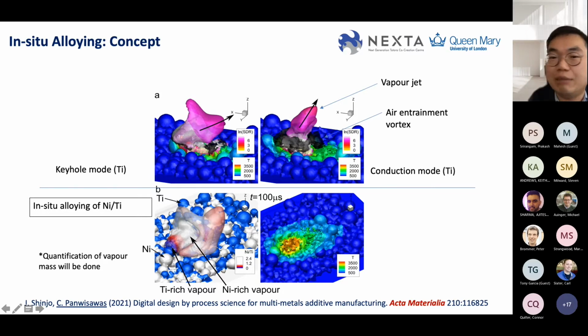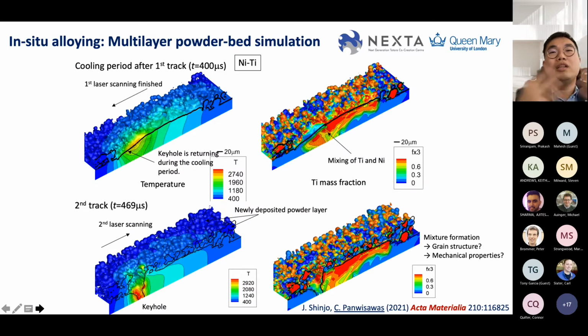That's why the title is called species mixing. So this is a concept, and once we implement this in a multi-layer part-scale simulation, you will see that now we don't have only a single material. We have nickel 50%, titanium 50% spread onto the bed, and then we can actually see how things mix together. And if you choose the wrong parameter, you will see very clearly that the mixing is not very good, and that is why defects emerge or form. And then you see after the second deposition, at this process condition, the mixing is quite good. But the question after this is how we can use this information further for microstructure development and property prediction as well.